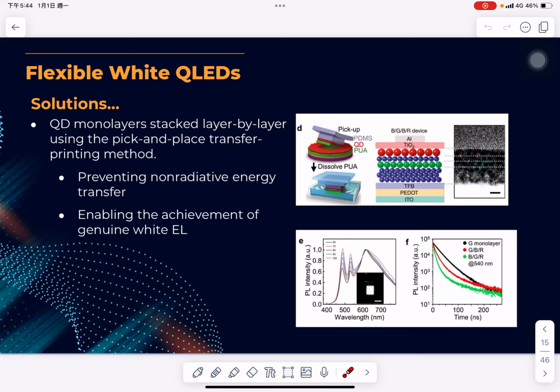SAIT group improved EL efficiency using quantum dot monolayers, stacked layer by layer, and using the pick and place transfer printing method. You can see the structure like this. Rearranging RGB quantum dot monolayers prevents non-radiative energy transfer and ensures genuine white EL.